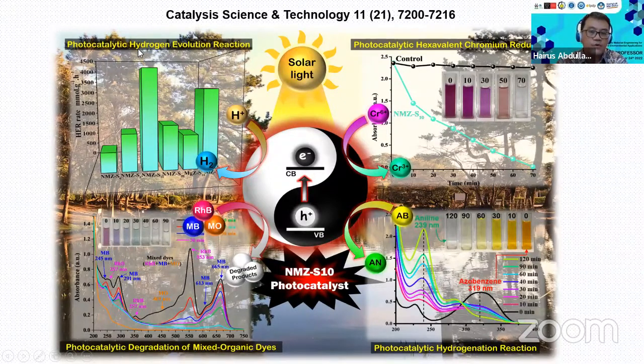So it's also very promising to evolve the hydrogen, and then it can also be used for hexavalent chromium reduction, right? For the second application, and then for the third application, we mix all the dyes together, like MB, MO, and RhB, right? Because these three kinds of dye can represent cationic, anionic, and neutral dye, right? So some of the work just show the application on the cationic dye or anionic dye or just neutral dye. But in this case, we try to mix all together, and you will see that this is very interesting: all the peaks of these dyes have been degraded right after the reaction.